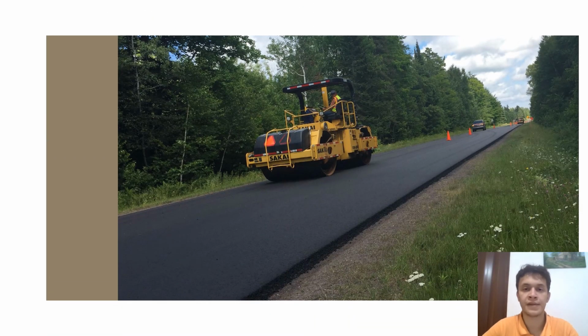In this presentation, we presented an analysis of the use of crumb rubber as an asphalt modifier. We could see that there are improvements in every physical and rheological property, an improvement in the rutting and fatigue cracking resistances. Drivers are guaranteed safer roads due to the homogeneous surface. States can build roads which are more cost effective. Also, there is a reduction in the maintenance exigencies, a reduction in pollution due to the lower carbon dioxide emissions. Large amounts of rubbish are recycled, which is what we are looking for.